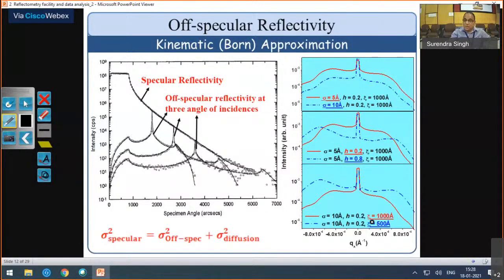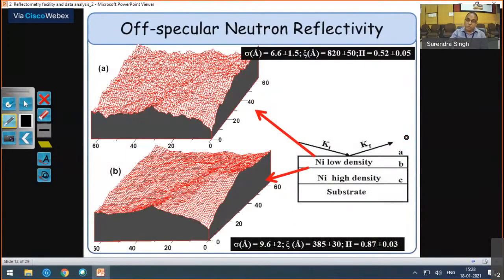From this figure, you can see if you change this parameter, your off-specular reflectivity pattern changes, and that's why you get information on interface morphology. Here I have shown two interfaces with different parameters, sigma, xi, and h. For this interface we have plotted this morphology. These values we obtained from specular neutron reflectivity, and then we generated these two-dimensional interfaces for these parameters, and for another interface.